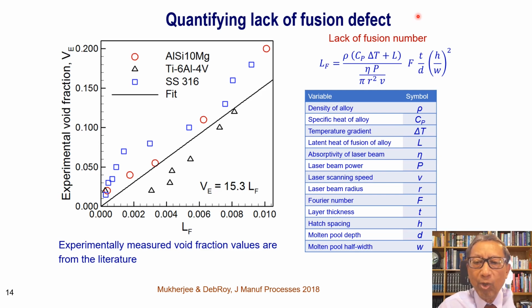We can use a similar methodology to build a model for lack of fusion defect. The final form is shown here, and the variables that are important are listed in this table. But in short, the lack of fusion defect is the ratio of the heat required to melt a unit volume of the feedstock divided by the energy supplied per unit volume multiplied by a Fourier number, and then this T is the layer thickness, D is the depth of penetration, H is the hatch spacing, and W is the width of the fusion zone. As you see, we will need the dimensions of the fusion zone in order to use this model. And those dimensions are obtained from a separate model.